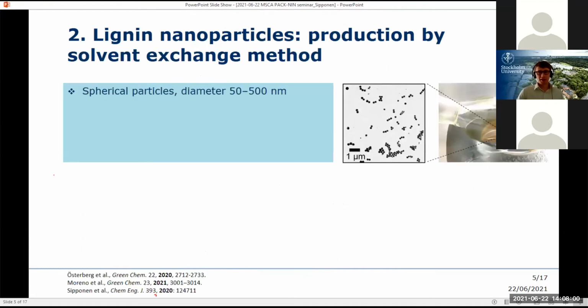So what are these lignin nanoparticles then? These are basically spherical particles. In recent years, a few different technologies have been developed to produce them. One of them is the solvent exchange or nanoprecipitation method, which produces particles in the size range of from 50 to 500 nanometers in diameter.